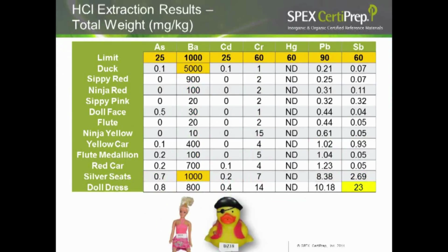If you look at the total weight way of calculating it, then most of the results do fit within the limit allowed. The only exceptions are for barium, where our friend the duck again became the villain of our story with 5,000 milligrams per kilogram of barium, and the silver seats in that little car were at 1,000, right at the limit. We also had antimony, which was higher than almost all the other samples we tested in the doll's dress. Now, it did not exceed the limit for antimony, but it was much higher, an order of magnitude higher than some of our samples.